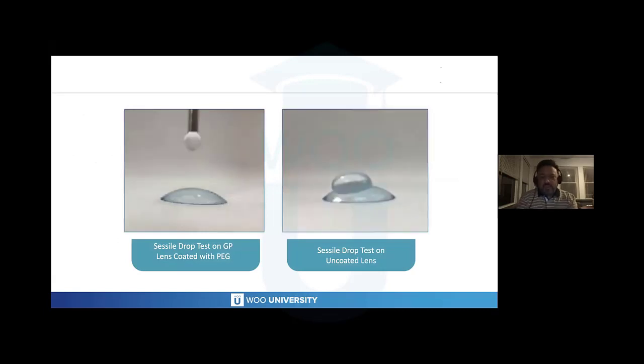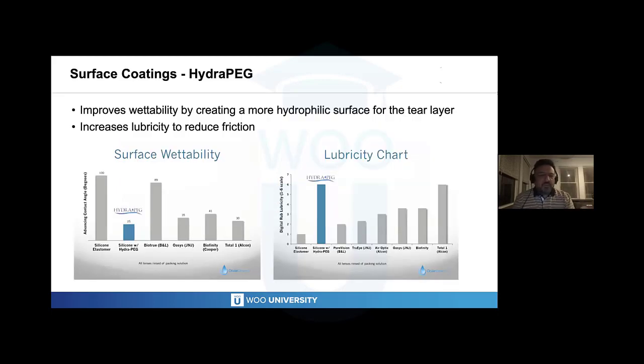This is just a little video showing the impact of doing a sessile drop test on a GP lens on the right that doesn't have any coating. This is just a standard GP lens. When we do put the HydraPeg coating on it, a dramatic difference in how that liquid spreads out over the surface. So there can be no question about the fact that coating that lens surface has a dramatic impact on the wettability of the lens. And here's just a couple charts that talk about that. Your chart on the left, which talks about wettability. The key take home of this chart is really the first two columns. A silicone elastomer with a contact angle of 100, applying the HydraPeg treatment to that silicone elastomer lens reduces the wetting angle from 100 to 25. So you have a fourfold increase in the wettability of that lens surface. So again, no question at all that adding this surface coating over the GP material has dramatic impact on wettability.